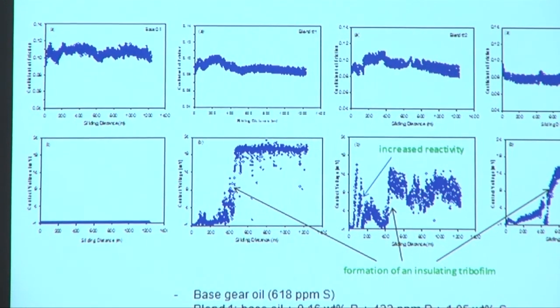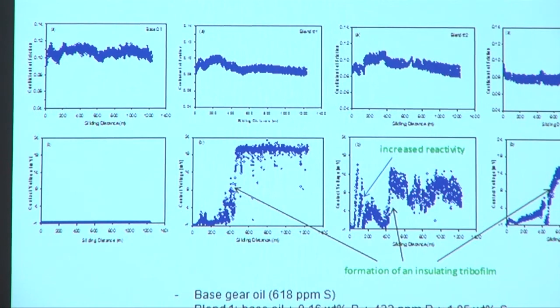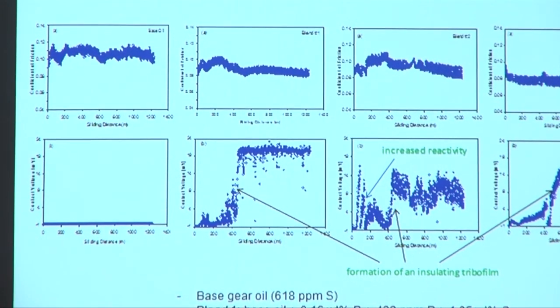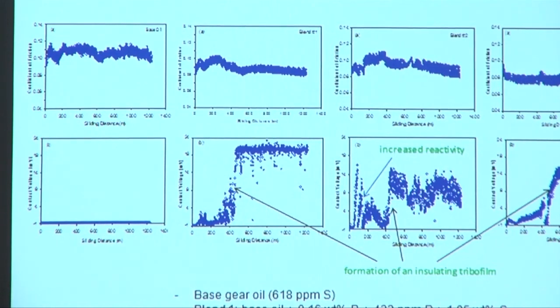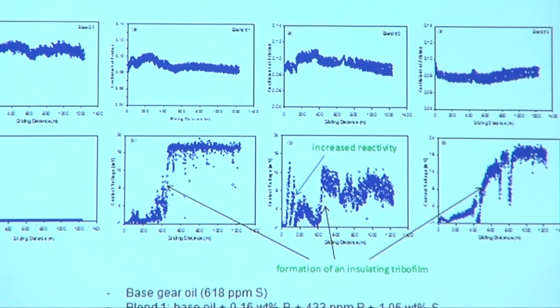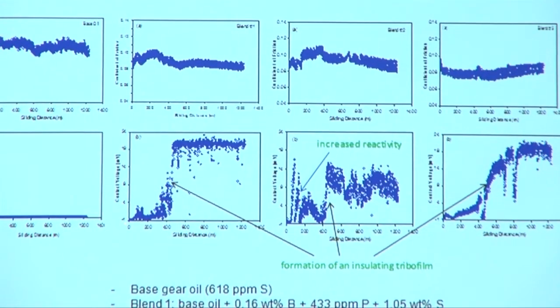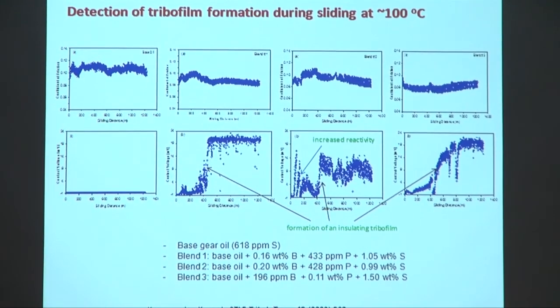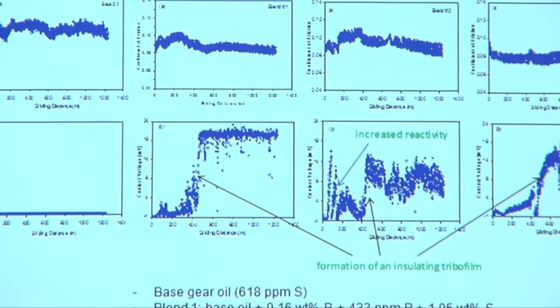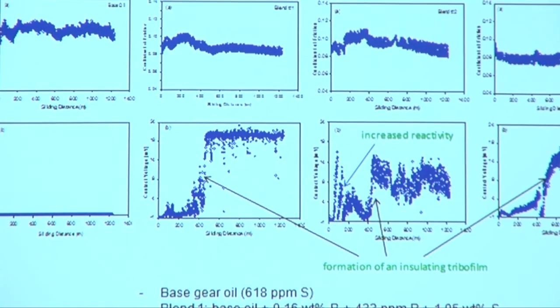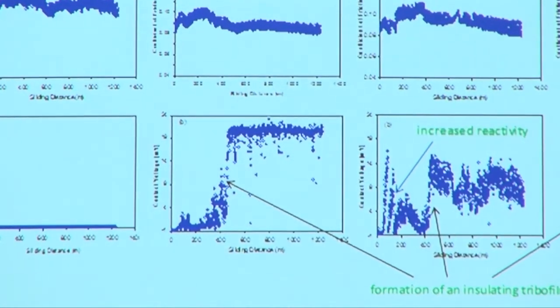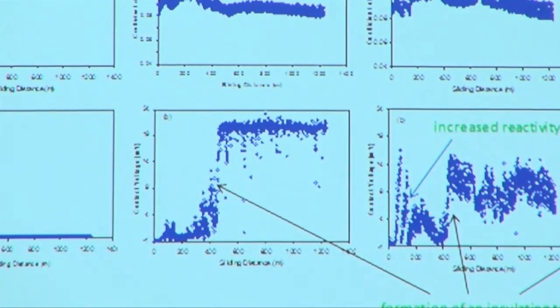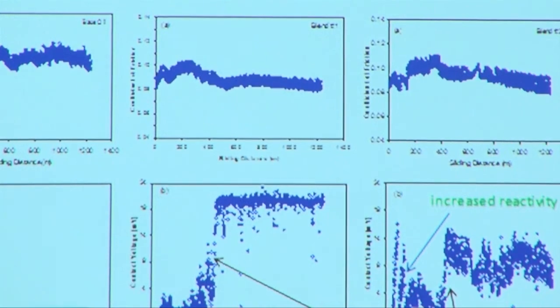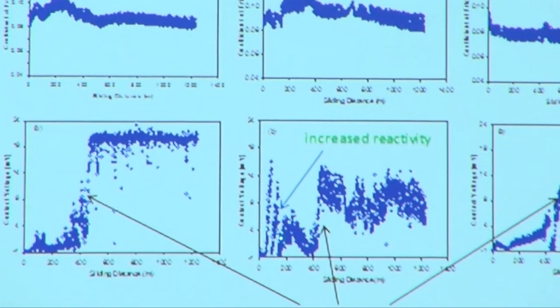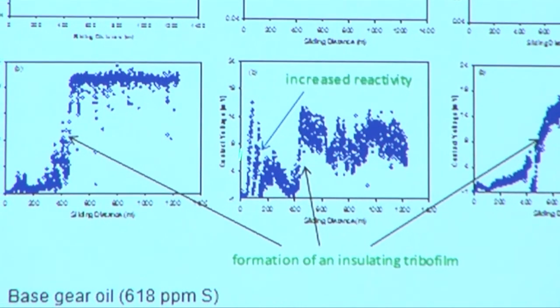This is, first of all, very thin and very fragile. And if it's something very thin, you can still have tunneling through that, so you will get zero resistance. Or more importantly, if it's fragile, it's removed, and therefore you have no voltage. Now in the case of the blend 1, we can see that we have an incubation period, some activity is happening, the voltage fluctuates, and after sliding for some time, we have a sharp rise and establishment of a high contact voltage at steady state. At the same time, the friction begins to drop. In the case of the second blend, we see that this is more unstable than that, but it starts to form earlier.